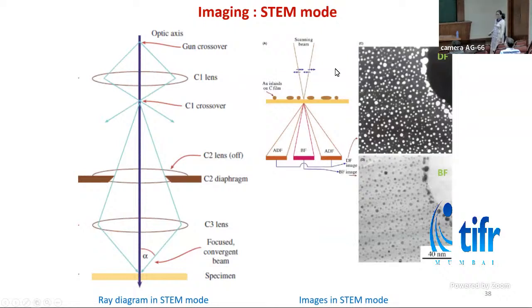STEM mode is used for analytical mode. So here the beam is focused and then moved across the sample, and this is the ray diagram in STEM mode. So here also we have a bright field detector, and because of mass thickness contrast, we can get, so these are the gold particles sitting on a carbon film, carbon grid. So that's why we can see that the gold particles are dark, and the grayish contrast is of the carbon grid. And this is the image taken using the dark field detector, which is the Z contrast detector. So here we can see the gold particles as bright and carbon as dark material.